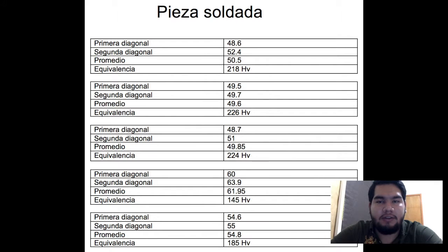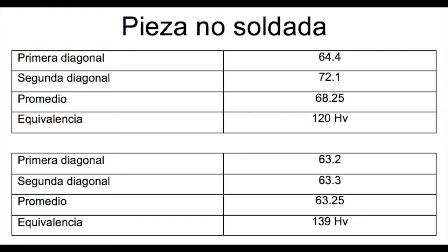In the Vickers hardness test for the steel with welding, we did 5 measurements, and for the one without the welding, we did 2 measurements. For each piece, we got the average hardness. For the piece with the welding, we got 199.6 Vickers hardness, and for the one without the welding, we got 129.5 Vickers hardness. This means that the welding process did increase the hardness of our piece.